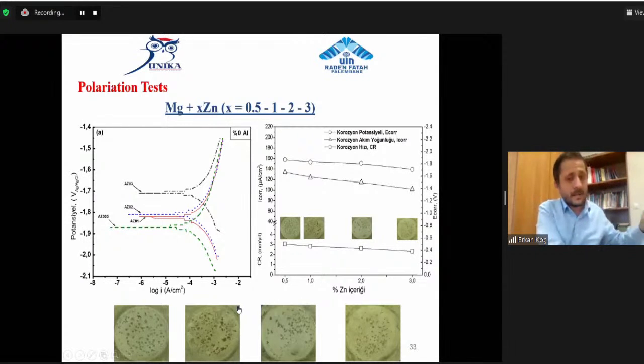And here is the electrochemical polarization test. When you see 0.5 zinc, increasing zinc in magnesium alloys, you see macro photos, decreasing corrosion rate, okay?